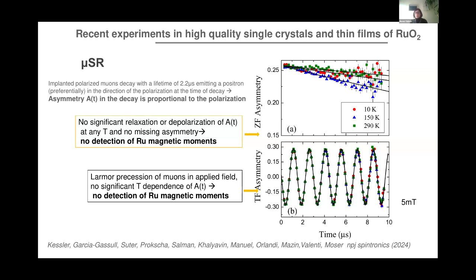What they observe, shown here as a function of time for different temperatures, is that they don't observe any relaxation or depolarization. There is no missing asymmetry, both in the case of zero field and in the case of a finite field, where you have the Larmor precession, and they don't see any asymmetry going away from the typical Larmor precession. So again, the conclusion is that they don't observe magnetism. There is no magnetism in these rather pure samples. They did these measurements in single crystals as well as in thin films. So the conclusion is that if you have a rather pure sample, pristine ruthenium dioxide is such a good metal that the magnetism is not there.